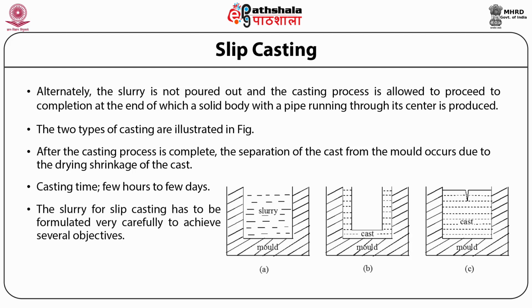The slurry of slip casting can be formulated very carefully to achieve several objectives. These include: the casting rate should be reasonably fast, the cast should have adequate strength for handling subsequent to drying after removal from the mold, the level of porosity in the cast should be as desired, and the cast should have uniform thickness.